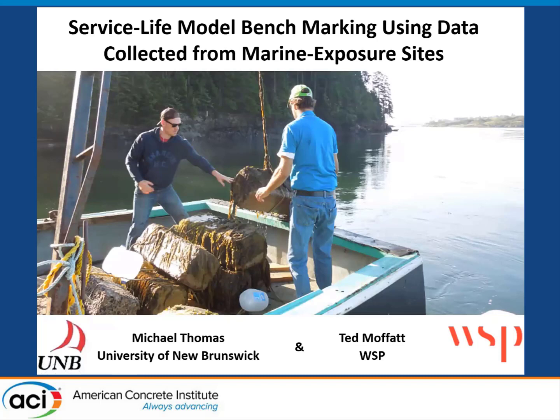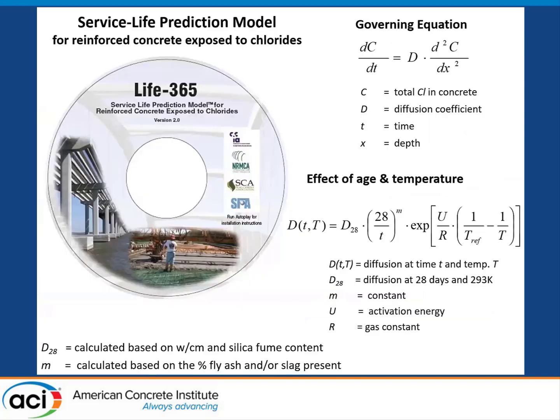Okay, so service life model benchmarking using data collected from marine exposure sites. I've shown some, but not all of this data in previous meetings. I'm going to be talking about two models here. Life 365, showing the governing equations there for chloride ingress, and the second equation showing the effect of age and temperature and how this impacts the diffusion coefficient at any time t and temperature T.